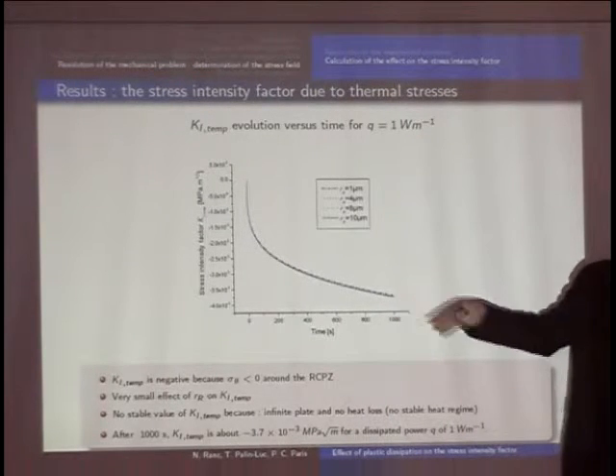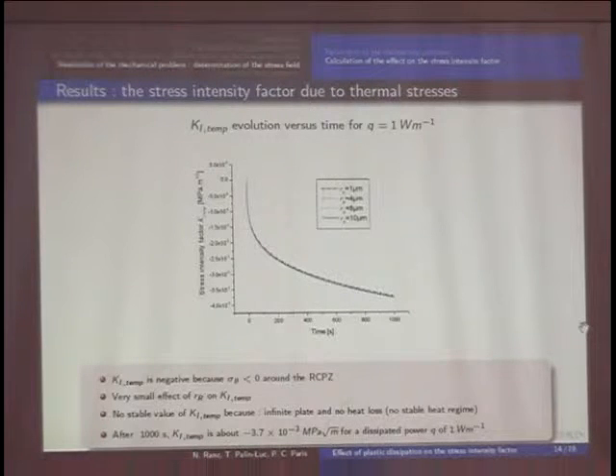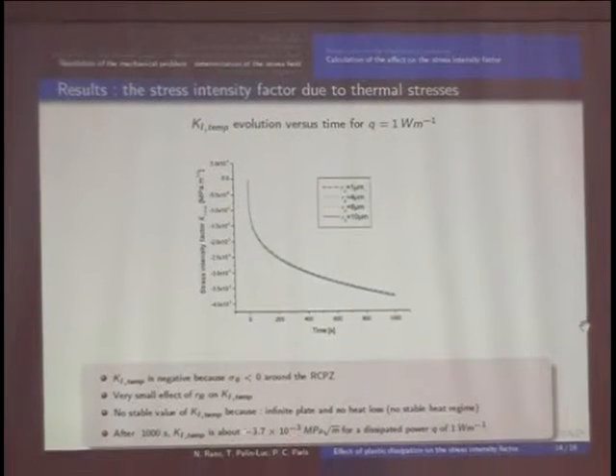And in our case, there is no stable value versus time. It's only an artifact of our problem, because in fact we have no heat loss, no convection, no radiation loss, and we consider an infinite plate. So in this case, there is no stable heat equilibrium. Of course, with finite element analysis, it's possible to solve a finite specimen and to include the heat loss. Here, in the case of a unit heat source, we can see that after 1000 seconds, the effect on the stress intensity factor is around -4 times 10 to the power -3 megapascals per root meter.